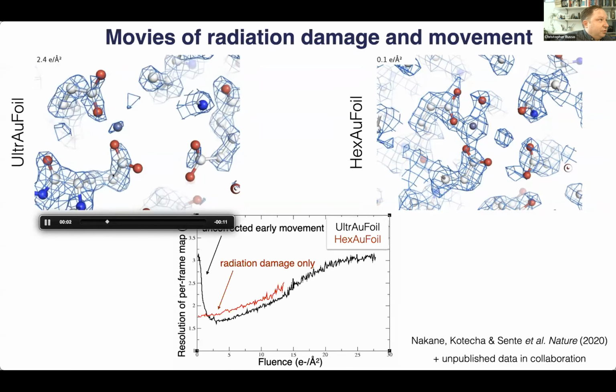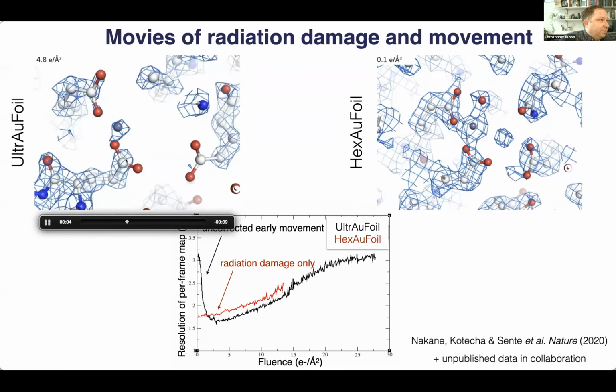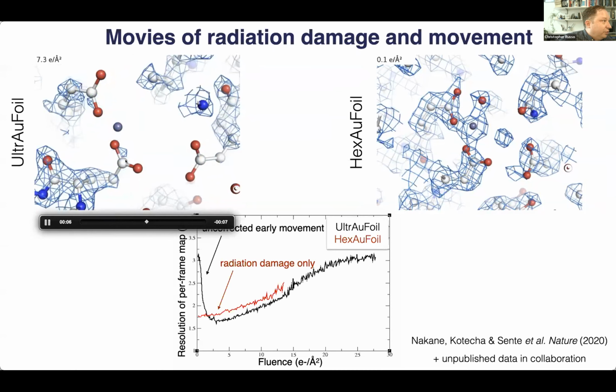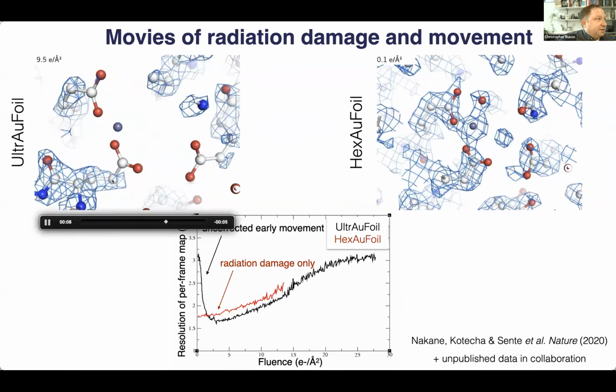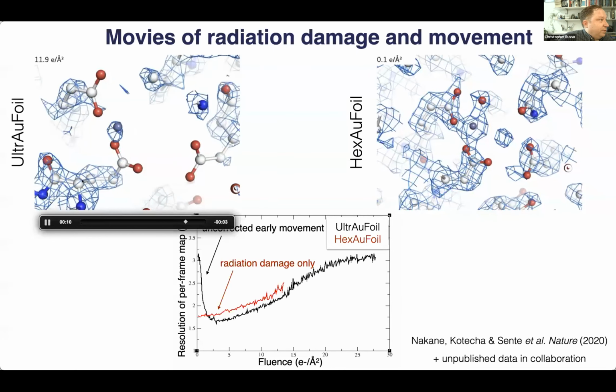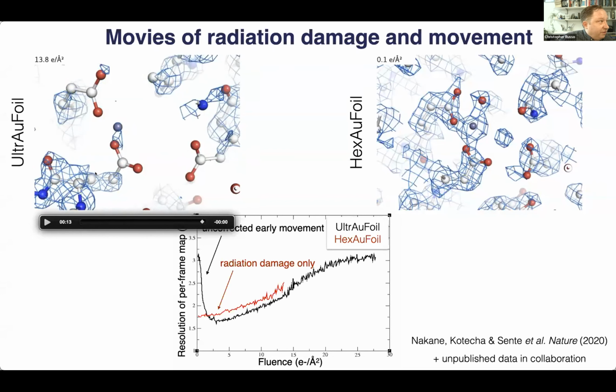And then as you progress to about 2 or 3 electrons per angstrom squared, it improves. And then eventually it decays again, as you might expect. So even in the very high resolution apoferritin structures that have been published, there is radiation damage incorporated, and the early frames are actually significantly worse.